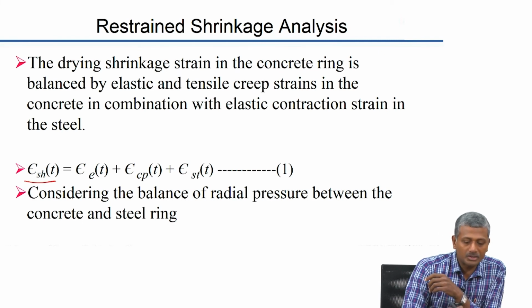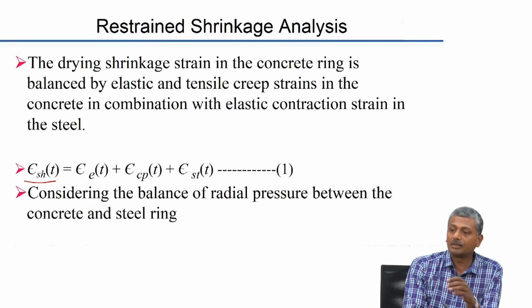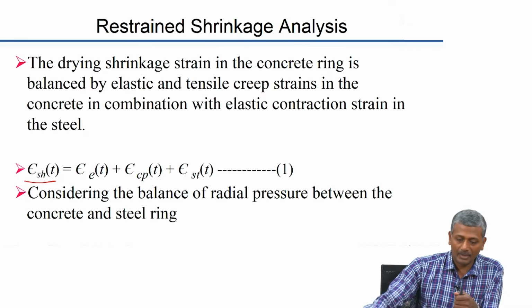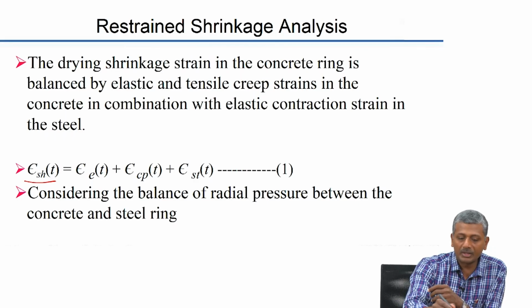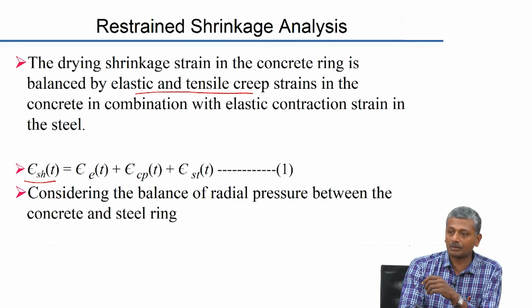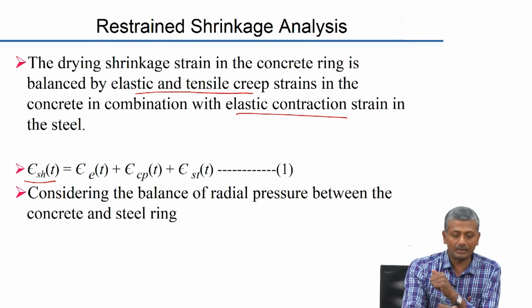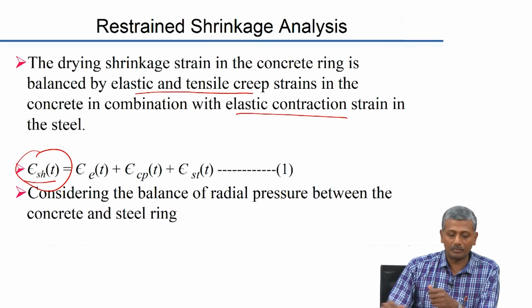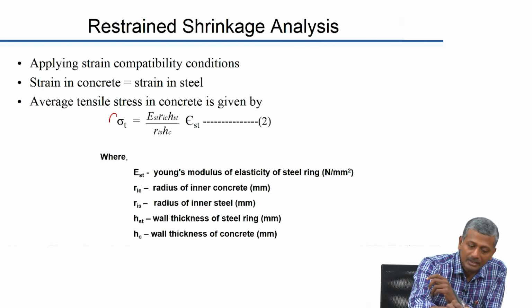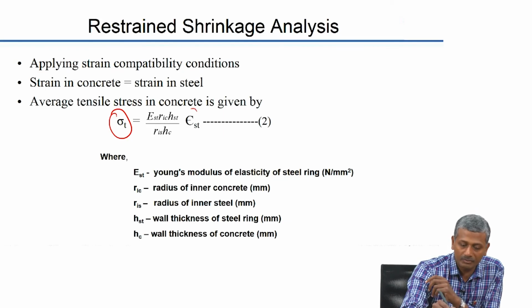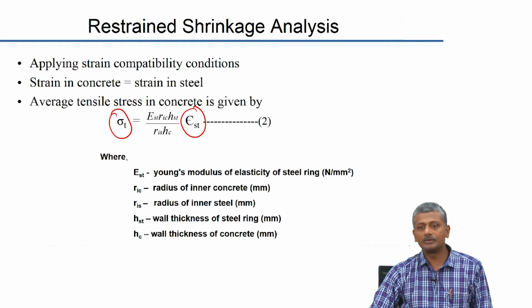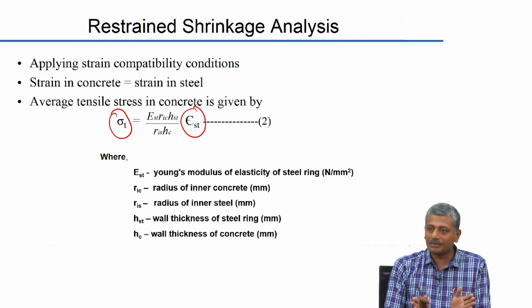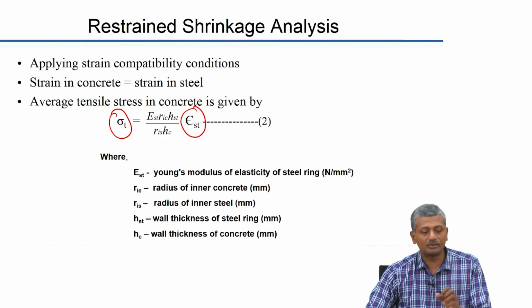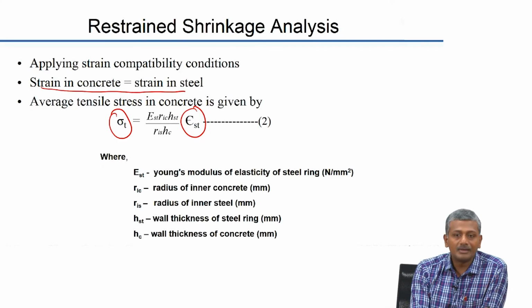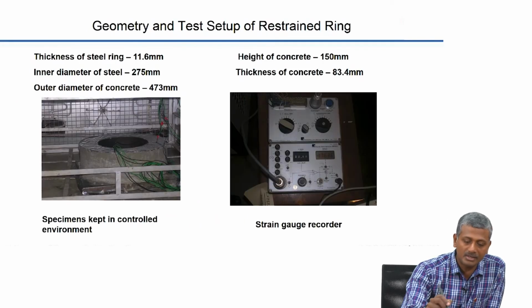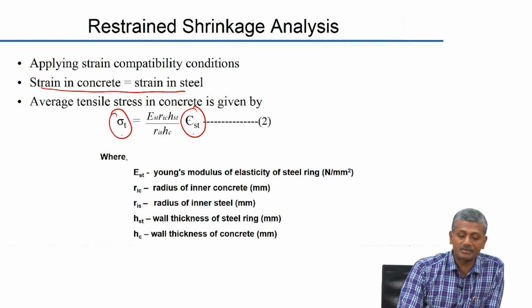So, here we consider the shrinkage to be a function of several different factors, because of the different elements that are involved with the system. So, again here, the total shrinkage in the concrete ring is balanced by the elastic and tensile creep strains in the concrete, okay, in combination with the elastic contraction strain in the steel. So, your overall strain is considered to be a mixture of 3 different components, and based on this you can actually work out the tensile stress generated because of shrinkage in the concrete as a function of the strain generated in the steel, okay, based on some boundary conditions that you need to apply in the system and considerations of drying happening either circumferentially or from the top and bottom. You can actually work out this kind of a system by assuming certain things like the strain in concrete is equal to the strain in steel. So, applying the strain compatibility criterion, you can actually obtain the stress in the concrete as a function of the strain in the steel.